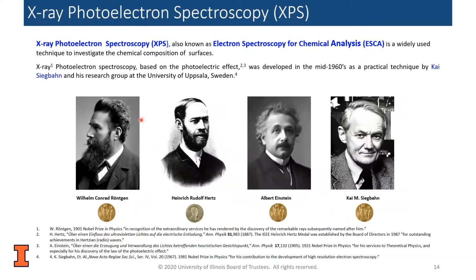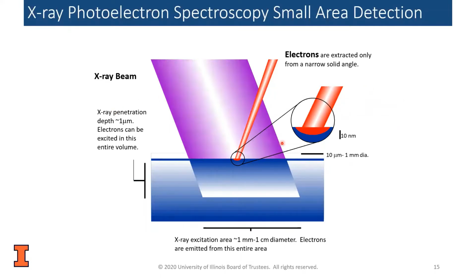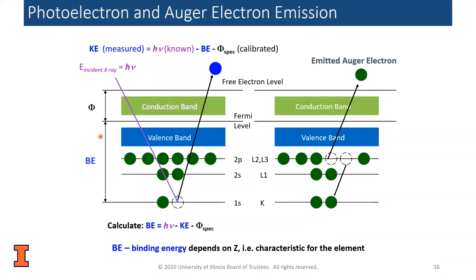XPS is a technique that's based on the photoelectric effect discovered by Heinrich Hertz and then described by Albert Einstein. And then later in the mid-1960s it was made into a practical analytical tool. The experiment consists of an X-ray beam, you irradiate a large area, and then we extract some electrons from a smaller area. How that works is the photon comes in, and that energy is absorbed, and then a photoelectron is released. This photoelectron will be ejected with a kinetic energy that is equal to how much energy was put in, minus how much energy is needed to hold the electron to the nucleus, that is the binding energy. Normally, when we look at XPS data, we'll plot it on a binding energy scale, not a kinetic energy scale. So we basically just swap these two terms.